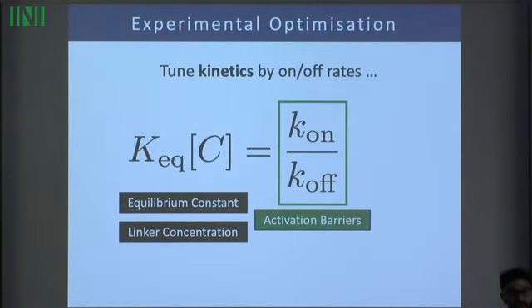And the way you do that is by activation barriers. When you have a binding event or an unbinding event, you can assume a very low activation barrier, in which case it's governed by the free energy change of binding. But you can also add a big hump in that reaction coordinate, and that hump has to be surmounted every time a bond forms or breaks. And that is how you tune your time scale.